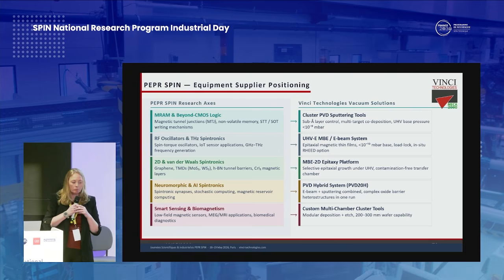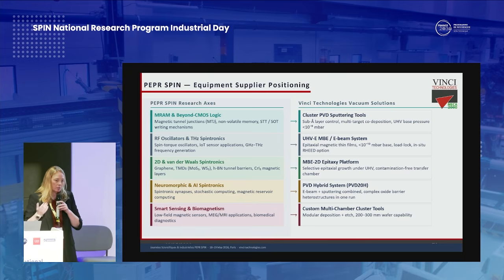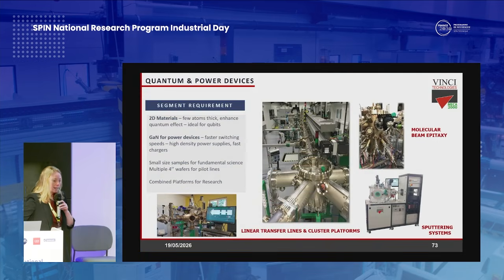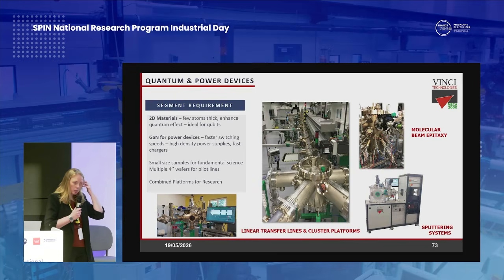Of the main research teams, we have the combined MBE and E-beam systems for the growth of different metals, and also for the growth of chalcogenides in the spintronic domain. We have our hybrid systems, as we talked about earlier on, which can combine organic growth and oxides and oxide preparation. And of course, the whole purpose of this is keeping everything under a UHV environment, because rising above 10 to the minus 6 millibar, as you all know here, can contaminate the surface, so we need to recover vacuum quite quickly.